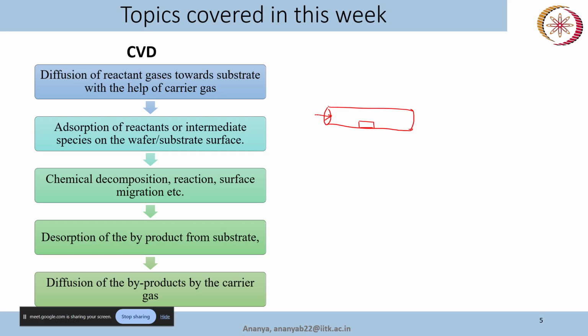From one side there will be a controller here, so that you will pass a very controlled amount of gas through this tube, and you often mix that with some carrier gas that will not interact with your material or with the substrate. This is just a carrier gas, and the pressure of this carrier gas will be higher, so that it can actually push the reactant gas towards the substrate. Okay, so the reactants will come here in vapor form. Now the reactant molecules will be adsorbed. You know what is adsorption? It is not absorption. It will sit at the top layer of the substrate, and that may decompose into other intermediate states of the reactants, which is the third process, chemical decomposition, reaction and surface migration.